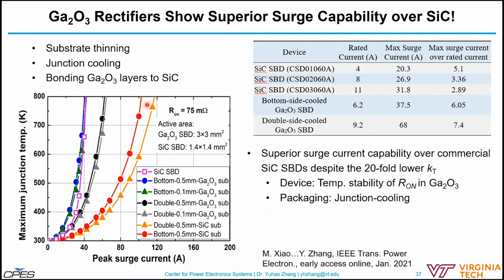And if we do the double side cooling package, probably the improvement is relatively incremental. How much this double side cooling can benefit compared to the bottom side cooling really depends on the intrinsic thermal resistance of the substrate. That's why in silicon carbide devices there is not too much need for double side cooling, because it does not bring too many additional benefits.